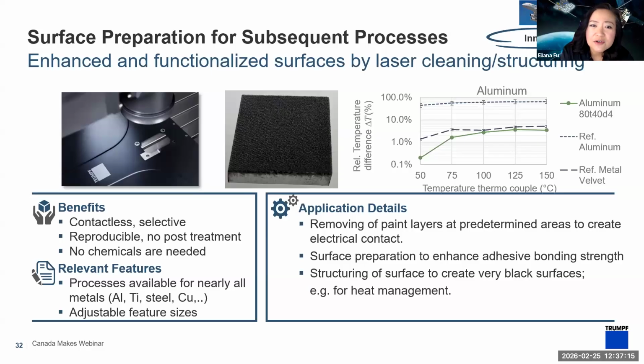Another one you can think of is to create functionalized surfaces using a laser. So again, we're only concentrating on the surface. So basically surface roughening, things like that, or creating different, what they call functions. So you remove paint layer in predetermined areas to improve electrical contact, or you do a surface roughening to improve adhesion if you're going to use adhesives later on.